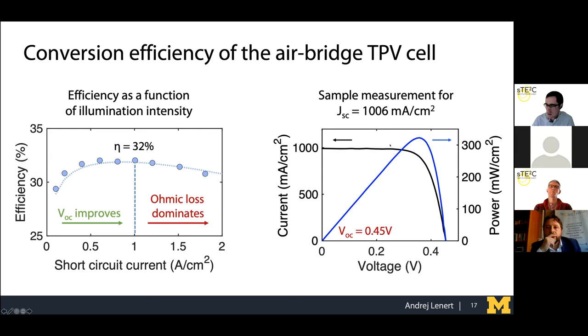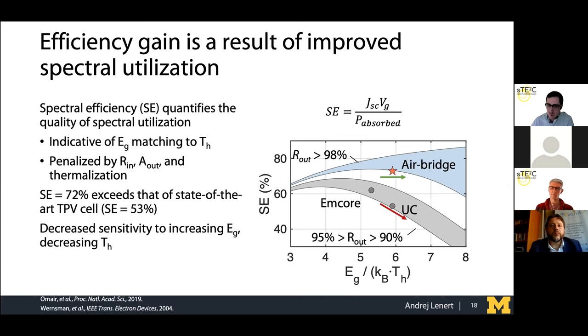One of the things I want to note is this is a very nice looking IV curve. However, our open circuit voltage is 450 millivolts, and I just want to say that there's some room for improvement here. If we look at the Berkeley group, they were able to achieve open circuit voltages closer to 530 millivolts. So the exciting thing is that if we improve the material quality of our epi film, we have another 10-15% improvement in efficiency that's really within reach in the short term. And I think the most exciting thing to me about the AirBridge architecture that we've developed is that it could be an enabler to reaching even higher efficiencies, and also an enabler to working with materials that are less expensive. And to the organizer's point, if we want to use thermophotovoltaics for solar, usually we're limited with the kind of temperatures that we have access to.